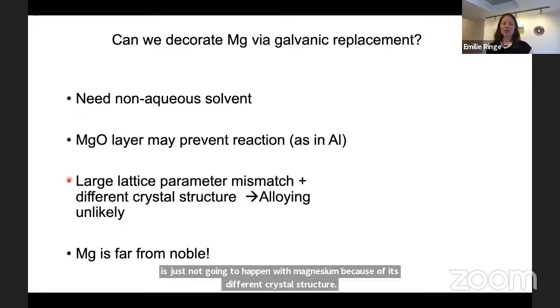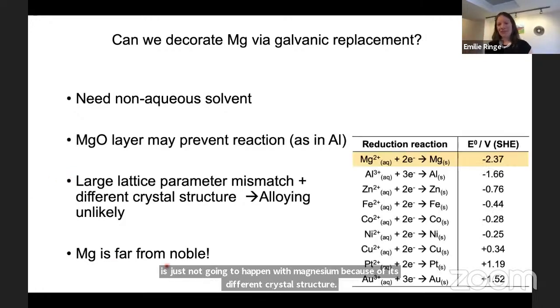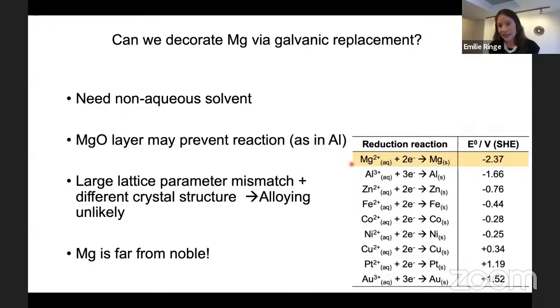But to our rescue is the fact that magnesium is really far from noble and is actually very likely to drive a reaction in which the magnesium really wants to get rid of its electron and something else wants to take it. So a huge thermodynamic driving force. And of course it works, otherwise I wouldn't be talking about it, right?